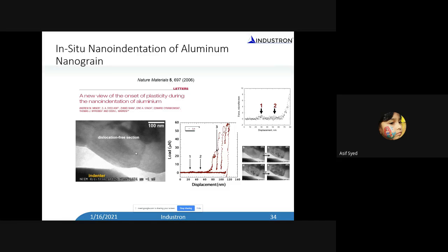We wanted to confirm that, so we did this experiment inside the TEM with this TEM nano indenter. This is the indenter tip. This is an aluminum grain, and you can have a two-beam condition in a way that we can find grains without any dislocation. You can see it's dislocation free. Now, when I do the indent, you can see as soon as it touches, it pops in nucleation of dislocations. These sudden dark things that you see are all dislocations. Correspondingly, you see the jumps in this load-displacement curve. From this curve, as well as from the image, we can calculate the stresses. We found the stress at the point when it nucleates dislocations is almost the theoretical strength of the material. So we gave a direct proof of what we believed, that the jumps that you see in this kind of material are due to dislocation nucleation and multiplication.